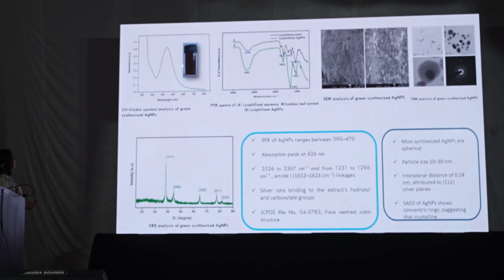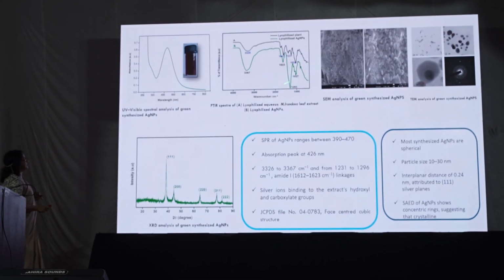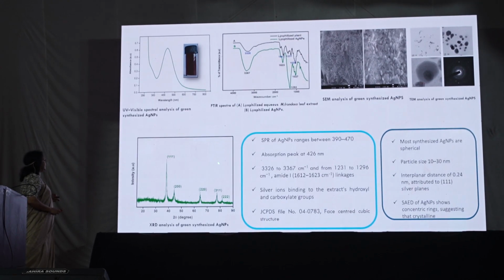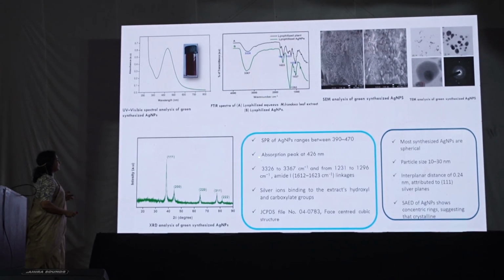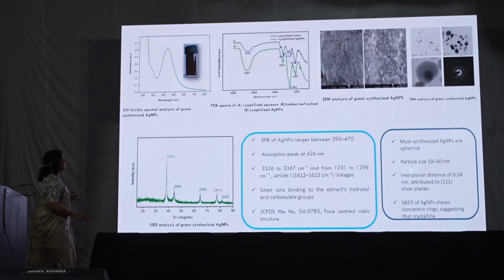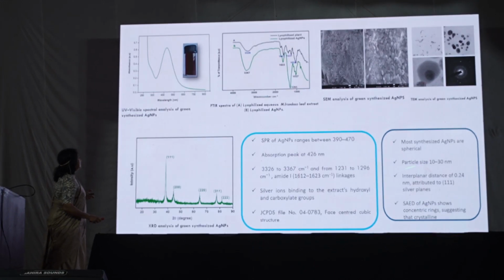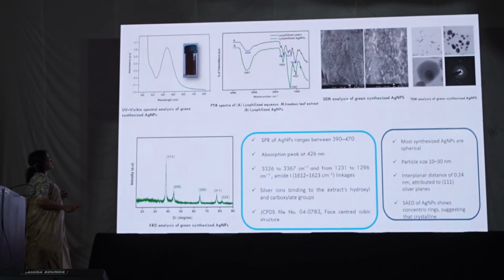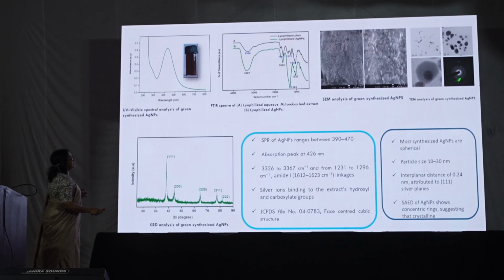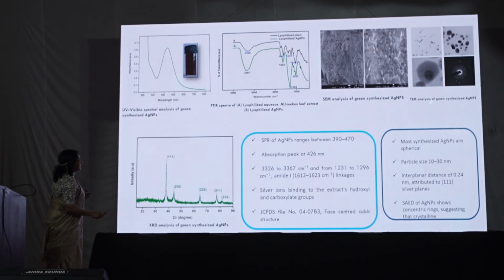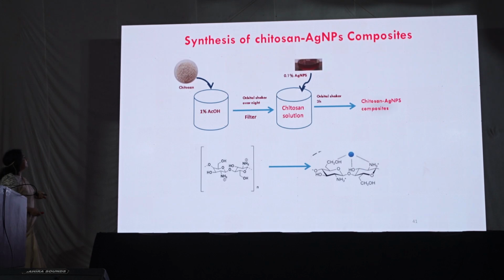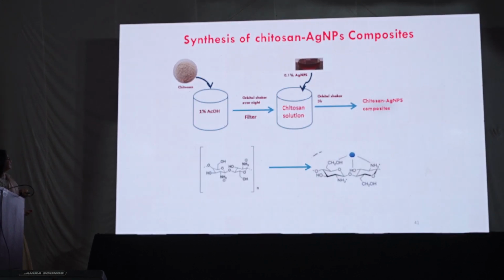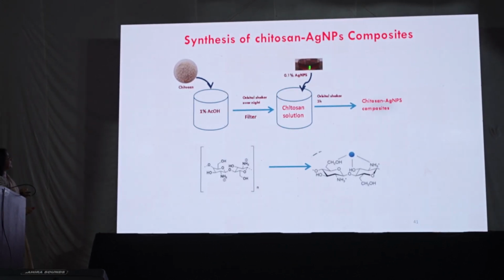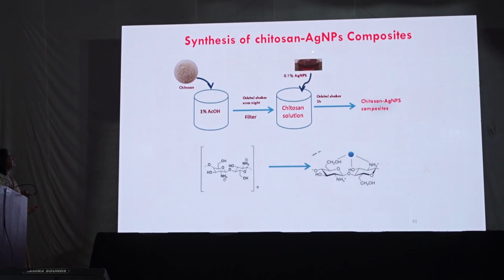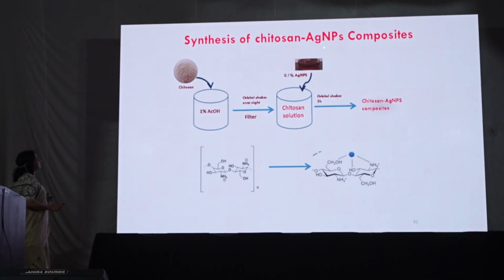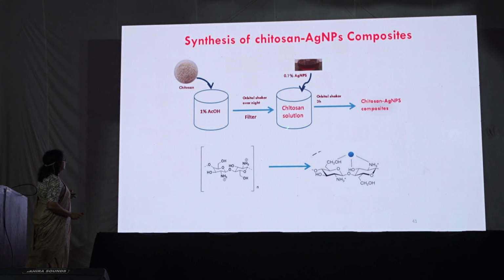And here you can see the color change of this nanoparticle solution, which is further characterized by FTIR, XRD, and TEM. The particle size we got was from 10 nanometer upward, and these were found to be crystalline in nature. From this we have synthesized chitosan, a biopolymer, chitosan silver nanoparticle bio-nanocomposites.